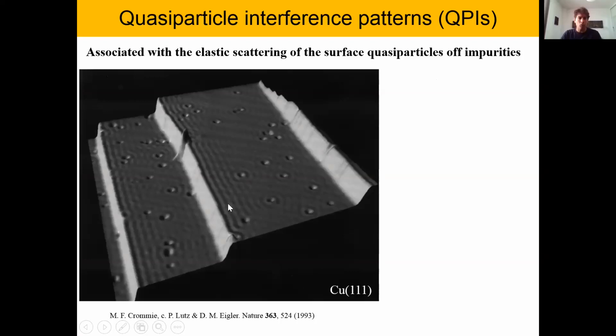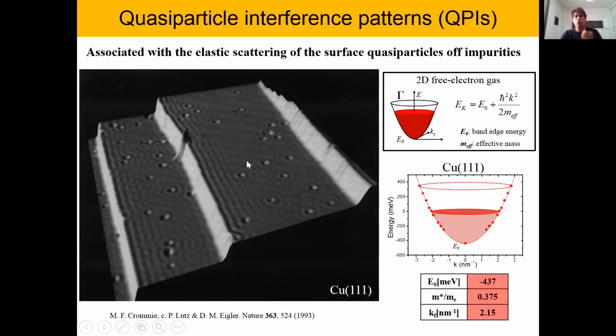In this seminal work by Crommie and colleagues, we can see the standing wave patterns that are formed on step edges or on different point defects that we have on the surface. And it was shown by Crommie and colleagues that analyzing these standing wave patterns as a function of energy, just measuring the period of these standing wave patterns, we can recover the band dispersion of our surface quasiparticles. In the copper surface, copper behaves as a two-dimensional electron gas, and then when we map the dispersion, we recover a parabolic dispersion. As I tell you, just analyzing this pattern and measuring the period of these standing waves.